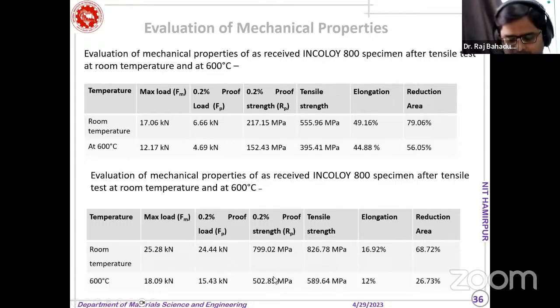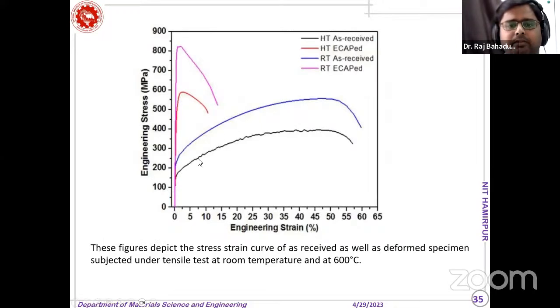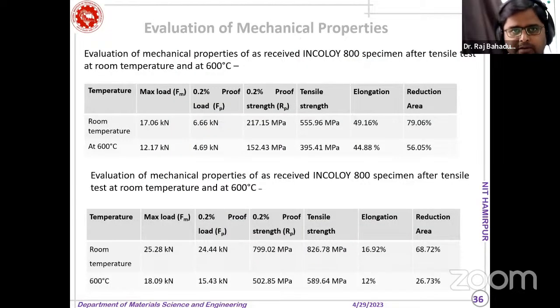Okay, so this is the graph. It shows similar things. We have this annealed material of Incoloy, and this is at room temperature, and this is at high temperature of the annealed material, and this is the graph of deformed material at room temperature, and this is the graph of deformed material at high temperature. So you can compare the annealed material at room temperature with the deformed material at room temperature, and the undeformed material at high temperature with the deformed material at high temperature. So the strength is improved. The reason, again, is the refinement of the grain size, increasing the grain boundary length, and increasing the dislocation density also.